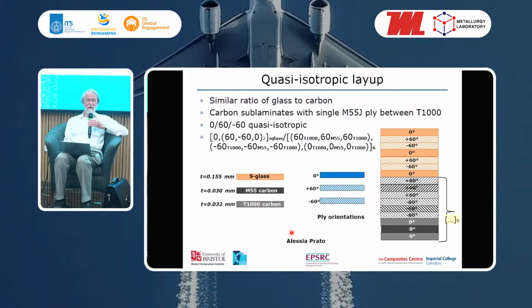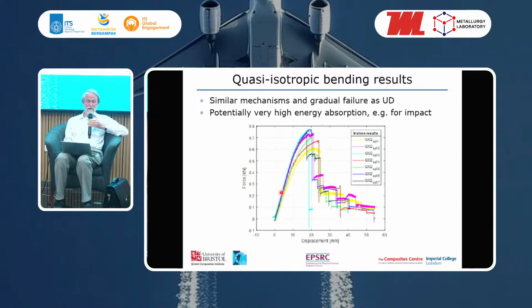We did a similar thing with the quasi-isotropic layup, whereby now we have a 0/±60 layup, glass on the surface, and carbon on the tension side. And again, this behaved very well. We got gradual failure, gradual fragmentation of the M55, and then progressive load drops on the tension side. So this gave us a similar mechanism of gradual failure as we saw on the UD, and potentially very good energy absorption, for example, in the case of dealing with impact. And even after all this, the specimen is still intact and able to take some load. It's not completely failed.